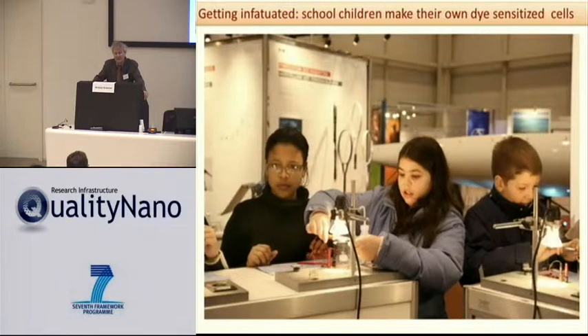I know of some titanium dioxide applications where they were putting them into polymers and had a big problem that the TiO2 produced radicals that then destroyed the polymer basically. What's your secret that your dye doesn't get destroyed by that?